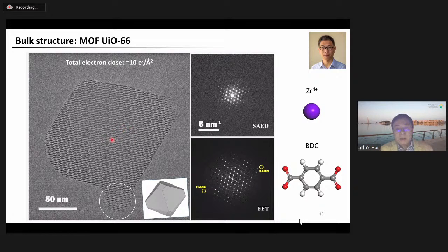And this is an HRTEM image of a MOF called UiO-66. This image was acquired with a dose of about 10 electrons per square angstrom, a very, very low dose condition, right? And the image resolution is about 1.5 angstrom. This high resolution indicates that the structure is well preserved.